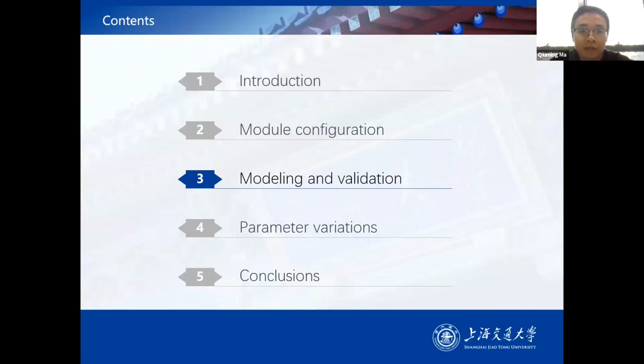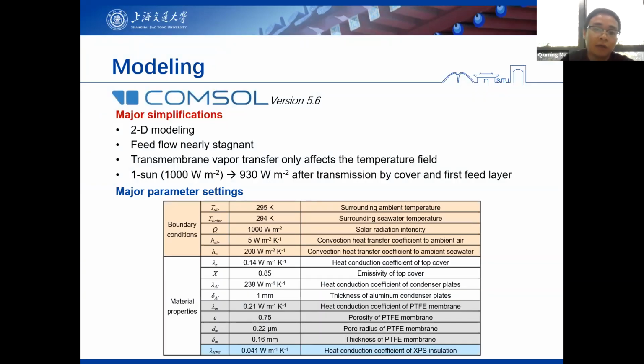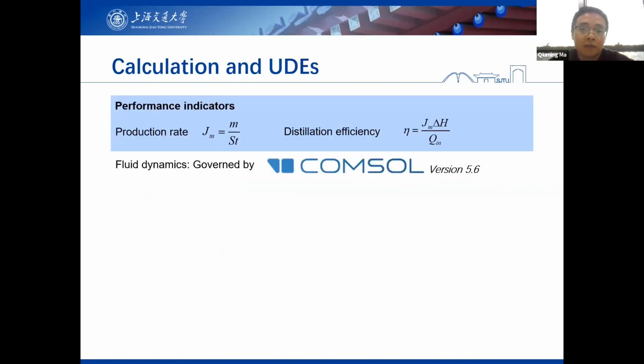After the experimental setup, now I'm moving on to the modeling and validation section. For modeling, we use COMSOL version 5.6 with some major simplifications as shown here. For the solar income, we assume a one sun condition, 1000 watt per square meter. But when we consider the transmission by the cover and first feed layer, which we also measured ourselves, we used about 930 watt per square meter for the solar income. The parameter settings are according to the real experimental conditions, as well as the real material properties. COMSOL doesn't have a specific module for membrane distillation, so we have to insert some calculations and some user designed elements.